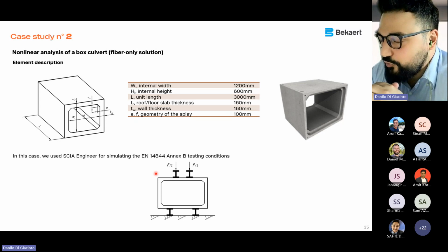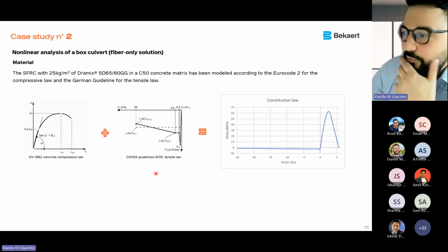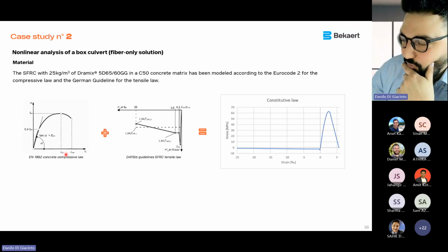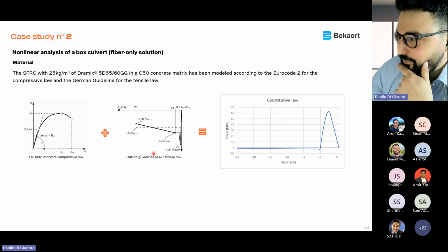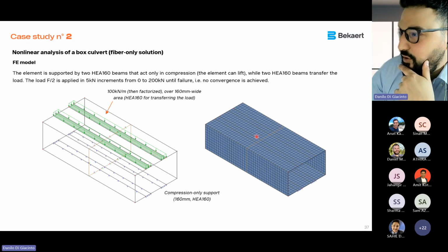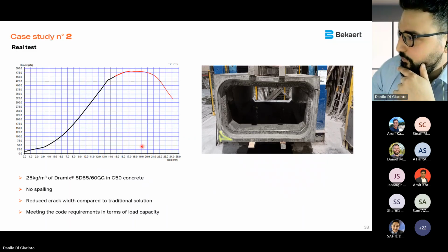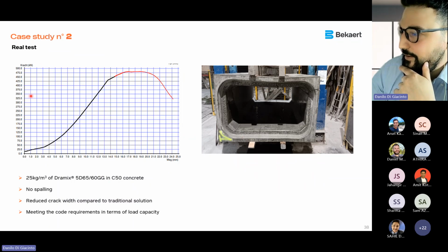What we did here, we did to optimize the resources for testing and nonlinear analysis with SCIA Engineer again, with as an input both the compressive strength according to the Eurocode and the tensile load according to the German standard. This is the model, very easy, with incremental load up to 200 kilonewton per line. And this is the real test. You can see here that even after failure, the structure almost reached 500 kilonewton with some pretty good ductility.